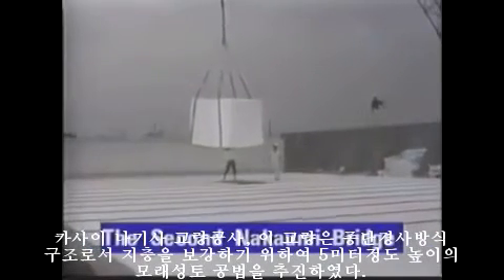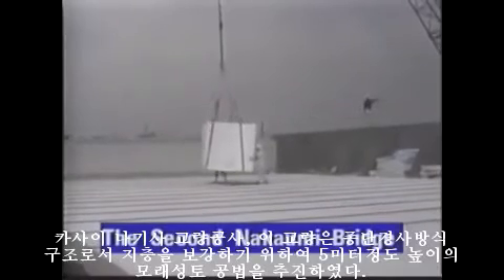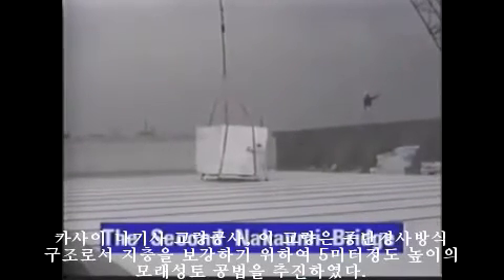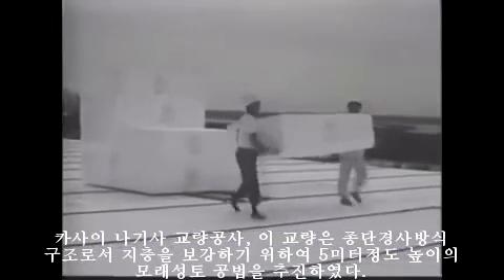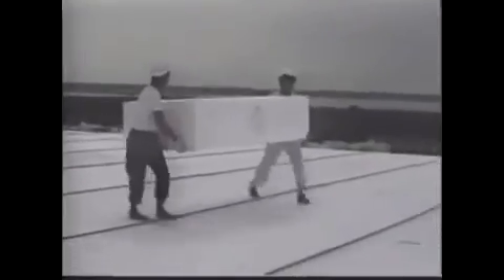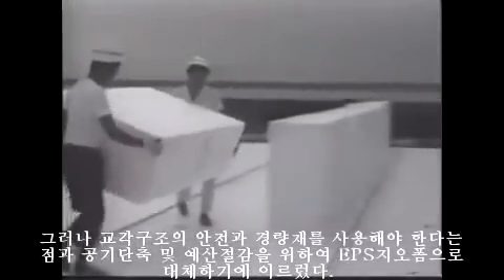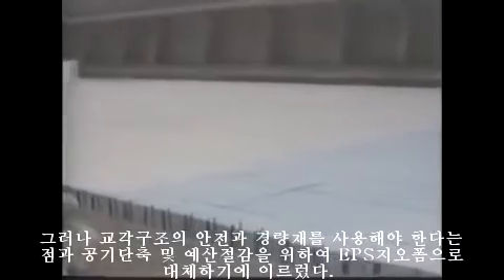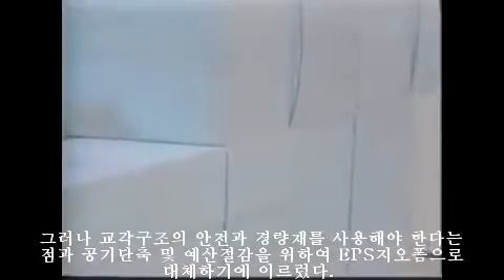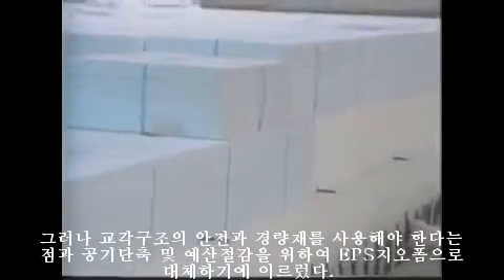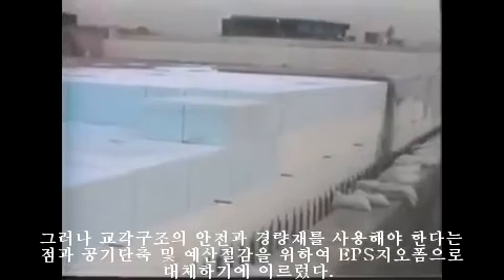For a similar reason, the EPS construction method has been used in connecting bridges, abutment backing, and filling for the waste disposal treatment sites at Tokyo Bay landfills. On this project, the top 20 inches of fill is extruded EPS foam material, and the balance is molded EPS. The combination of geofoam fills provided both very lightweight material along with very high compressive resistance in response to the anticipated load.